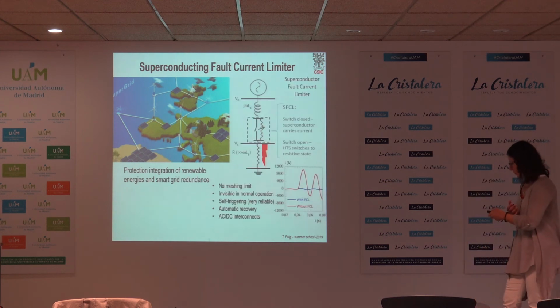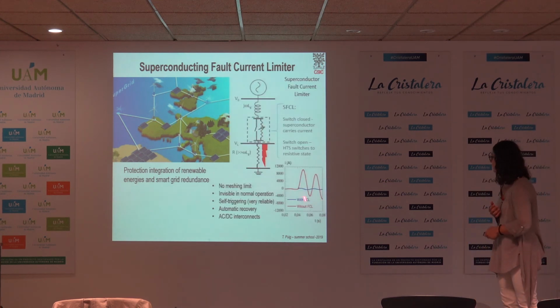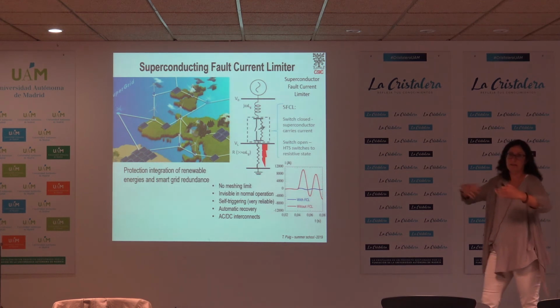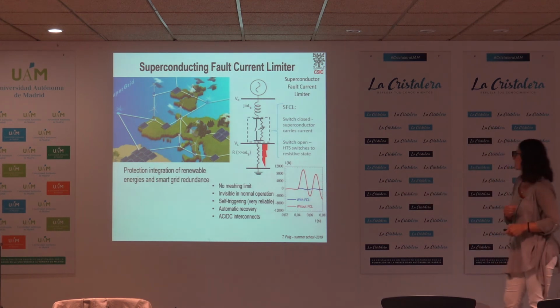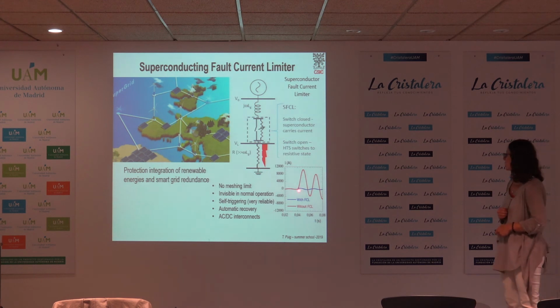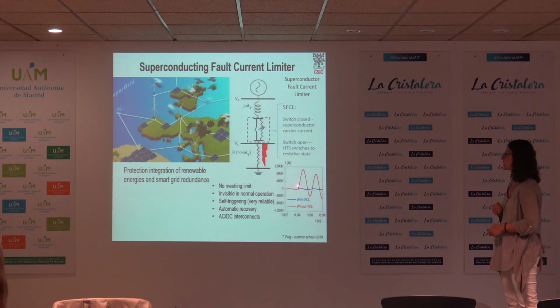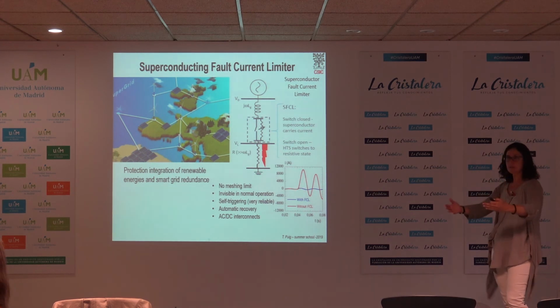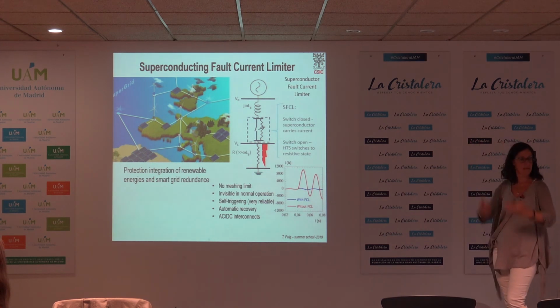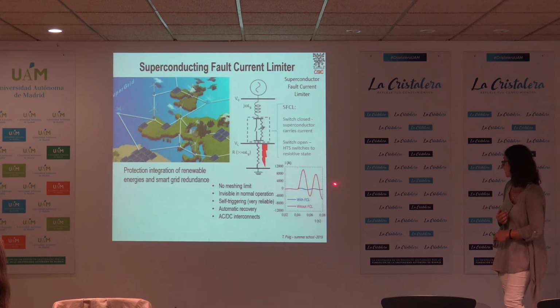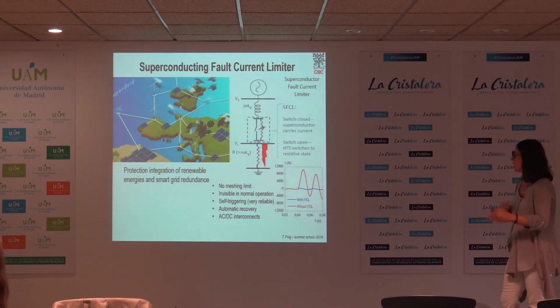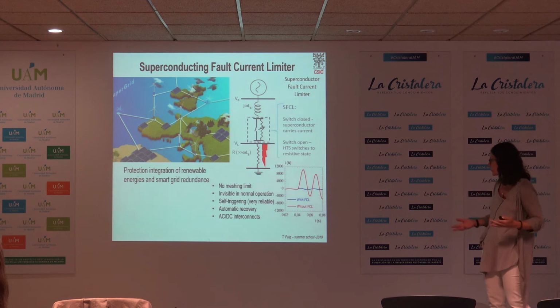Right? So this is what you see here, for example. This is current versus time. When there is a current fault without the fault current limiter, you have very high currents, which in the end is what destroys the equipment that you have in the network. If you have a superconducting fault current limiter, as soon as the current increases, this impedance avoids the current keeping on rising, and therefore it decreases the current. So this is interesting to be able to do parallel meshing in the network.